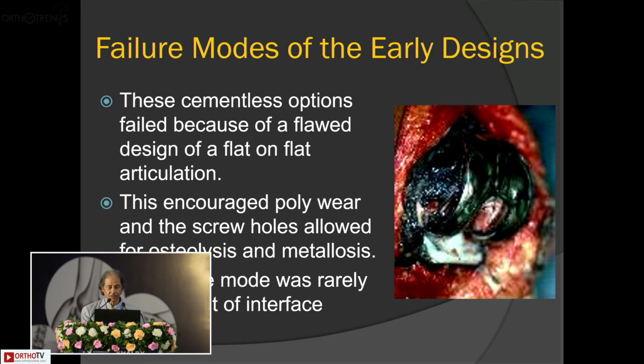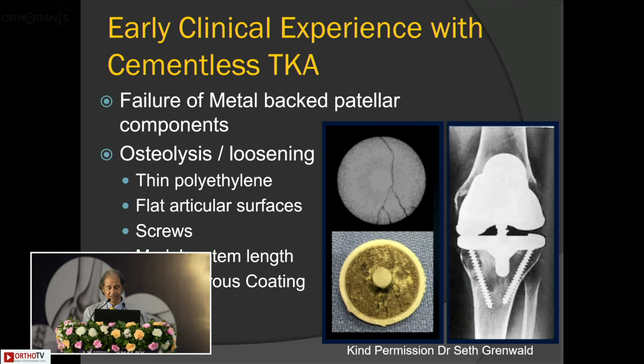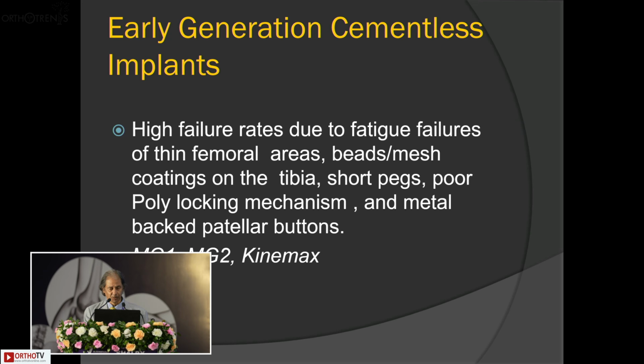And this happened because of the flaw of design of the flat articulation, the screw holes that facilitated osteolysis. The failure mode was rarely on account of interface failure, so that again was a positive. The biggest disaster really was on metal back, cementless, patella implants, and this was a learning for most of us.